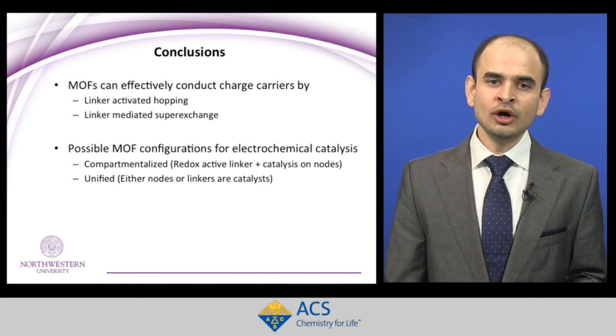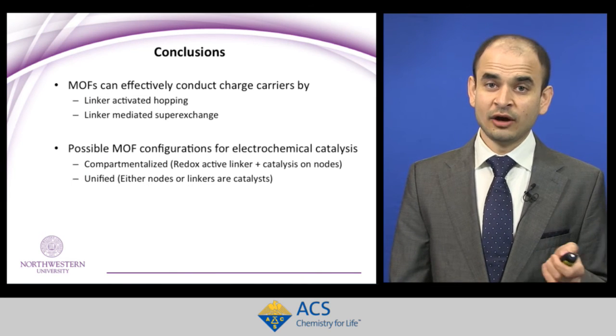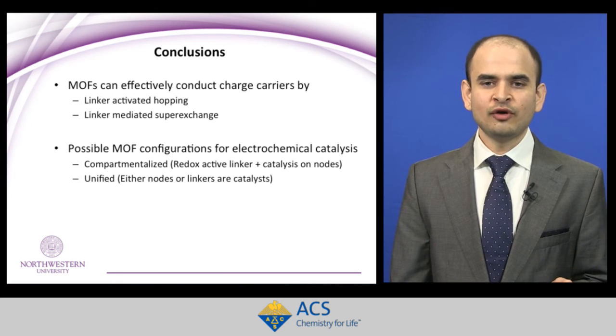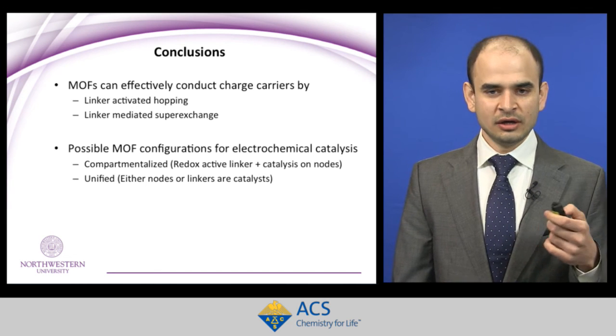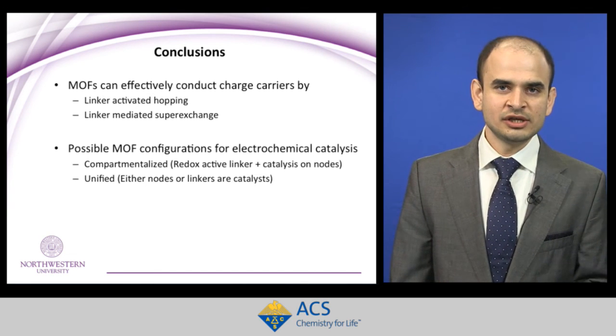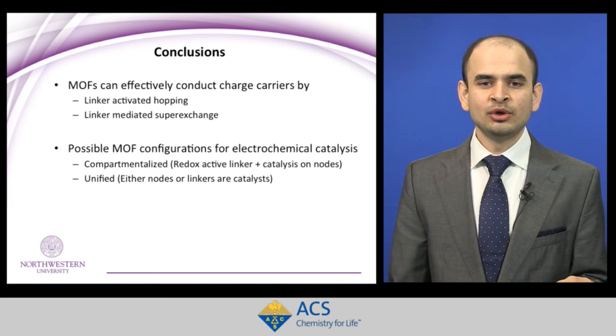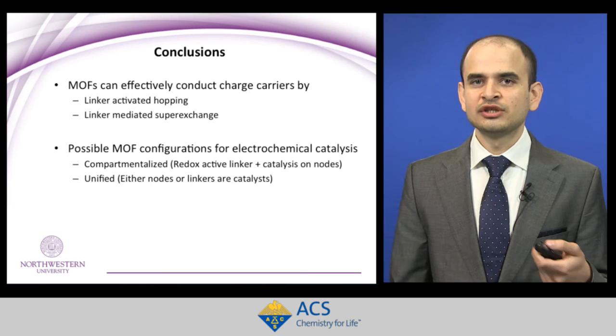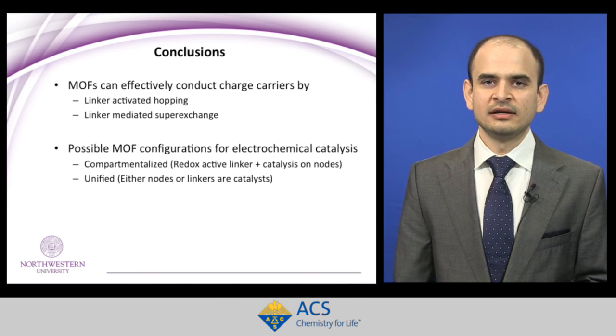To conclude, MOFs can effectively conduct charge carriers by linker-activated hopping or by linker-mediated superexchange. Possible MOF configurations for electrochemical catalysis are either compartmentalized — that is, redox-active linkers transporting charges and catalysis happening on the nodes — or unified, where either the nodes or the linker function as both charge-transporting material and catalyst.